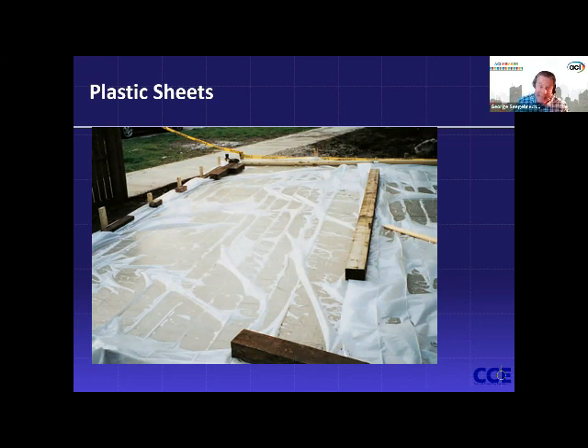Lay it flat is the easy answer. People go, well, I don't want to lay it flat. Well, then I can't help you. If you can stretch it out and lay it flat, and then put, say, an insulated blanket down on it, those battens that are a little stiffer can help keep that down. I had one job where they put styrofoam on top because it kept everything nice and flat, but you had to weigh down the styrofoam too from being blown away. But then if you put this wood on top of the styrofoam, there won't be any kind of mark from the styrofoam that would have been dissipated through the fiberglass.